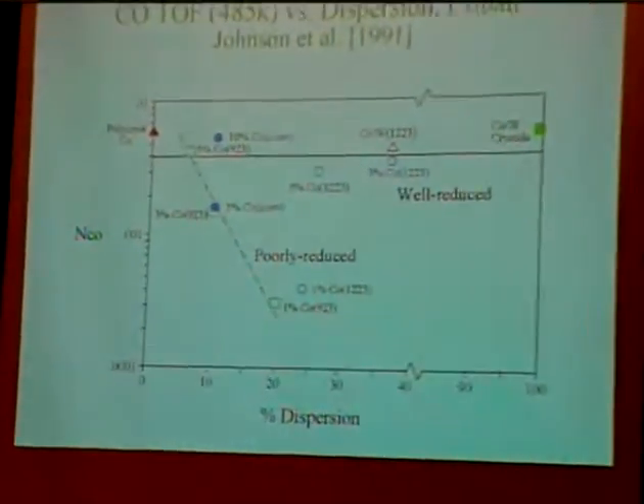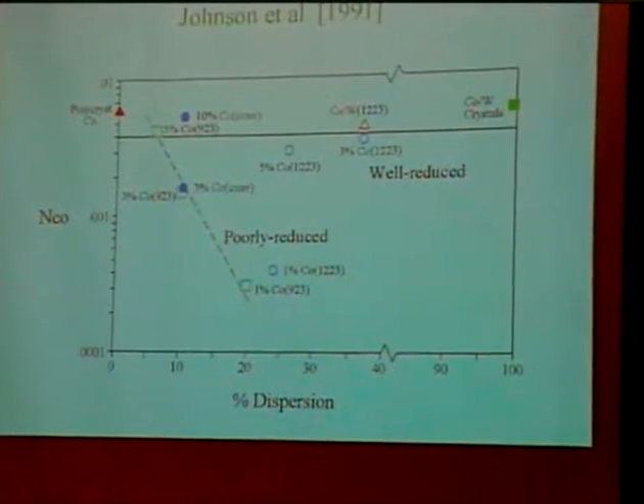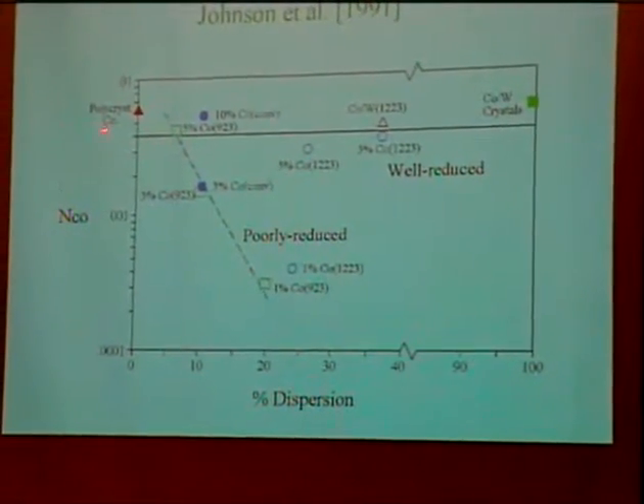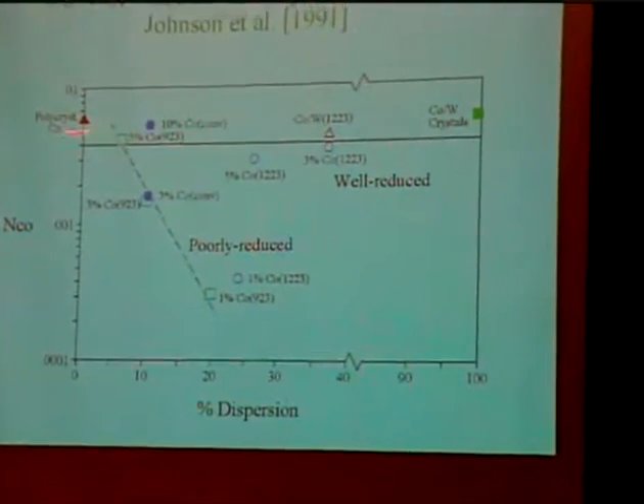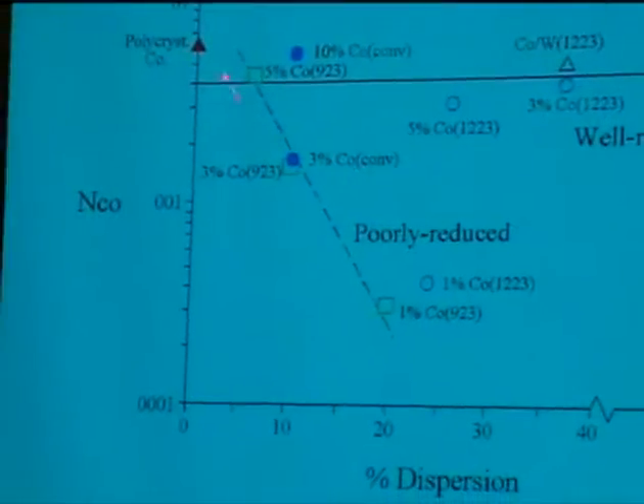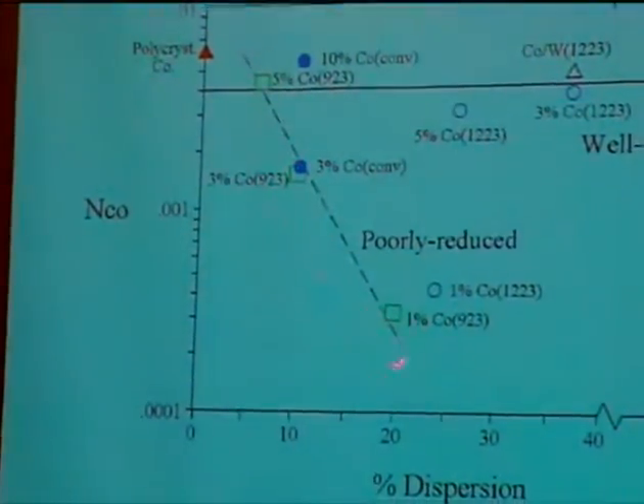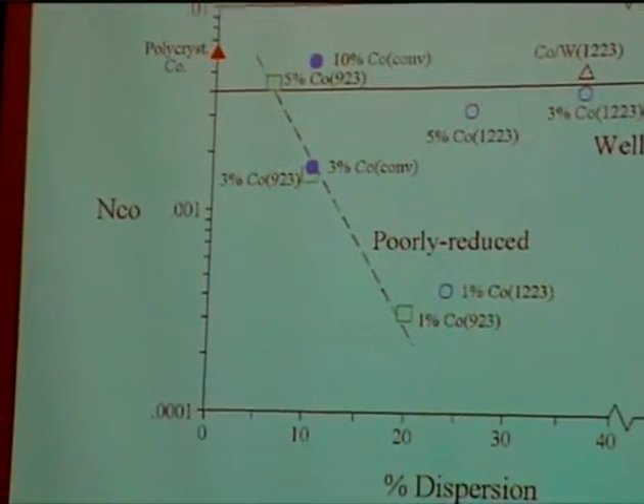For catalysts of higher loading, well-reduced catalysts with extended reduction greater than 60%, the specific activity is independent of dispersion from essentially 0 to 100%. On the other hand, for poorly reduced catalysts, less than about 50% reduction, and low metal loading, activity decreases with increasing dispersion.